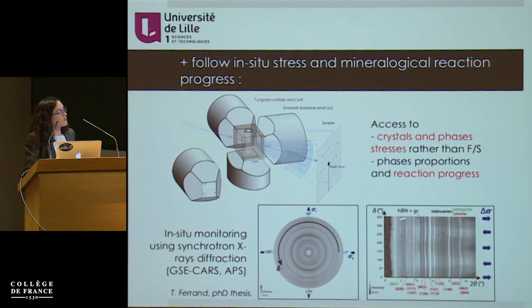So what you will access with this kind of thing, which is the analysis of the diffraction signals that is here, you can access the crystals and the phases stresses rather than the force over a surface. And this is a very important difference between this setup and the other ones. And you will also access the reaction progress because this diffraction signal here has signal that comes from here. It's an example on an antigorite and olivine, so polyphased aggregate. And you have signal coming from the olivine and signal coming from the serpentine.